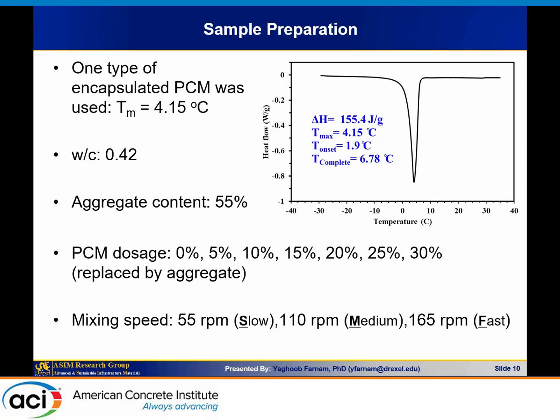This is heat flow as a function of temperature. As we decrease the temperature, we get a phase change, seen as a big peak or spike in the heat flow. That spike or peak is the phase change formation, because in any phase change, this is a principal physical phenomenon, liquid to solid, the latent heat of fusion is released or absorbed. That peak is the heat release. If this heat release gets bigger, you will have more energy inside your system. So this is a DSC, differential scanning calorimetry, result of the PCM that we used.